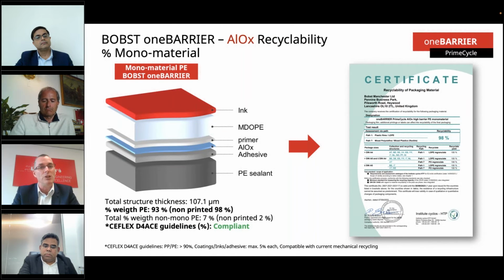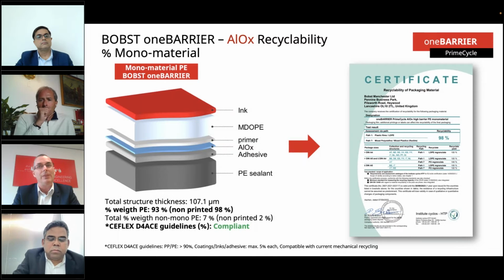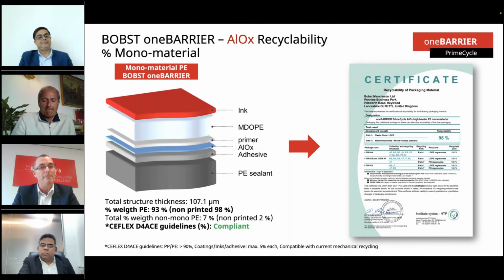So just to help illustrate the potential recyclability of the solution via the amount of monomaterial in the one barrier structure, in this case we've used a 25 micron MDO-PE film, and the sealant web is based upon a 75 micron PE sealant web. If we use the mass balance of the polyethylene, we have a monomaterial weight percent of around 98% in the case of the non-printed structure, or 93% in the case of the surface printed solution. So in both cases, we are greater than the 90% CEFLEX guidelines, even for this relatively thin duplex structure.